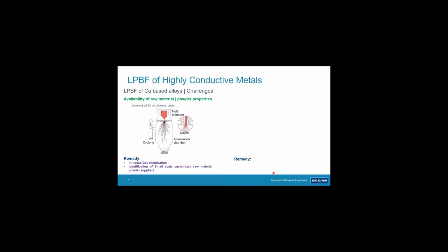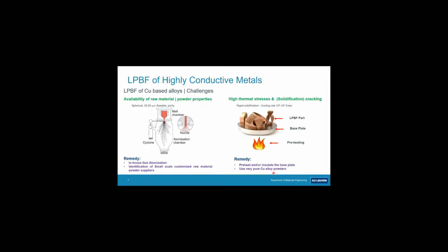First of all, when we talk about copper and copper-based alloys, of course, you need an adequate powder, which in most cases here we atomize ourselves using a conventional close-coupled gas atomizer. The challenges related specifically to copper: you all know that in solid state, copper is a good conductor. So when you build it on a base plate, and we preferentially wanted to use copper-based base plates not to contaminate the bottom layers of the part, there is a lot of heat dissipation in the vertical direction. So it might be necessary to preheat your base plate to avoid the very rapid heat dissipation. That is foreseen in one of the non-commercial machines which we use and which were initially developed by our colleagues from the mechanical engineering department.